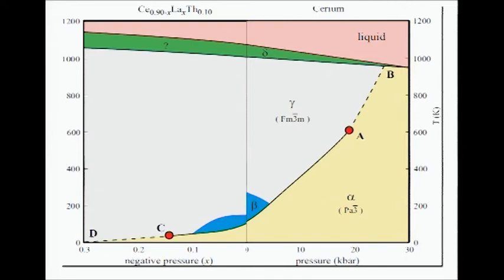So when you add in lanthanum, it drives the alpha-gamma transition temperature down. And at about 14% lanthanum, we see another tricritical point on the negative pressure side.